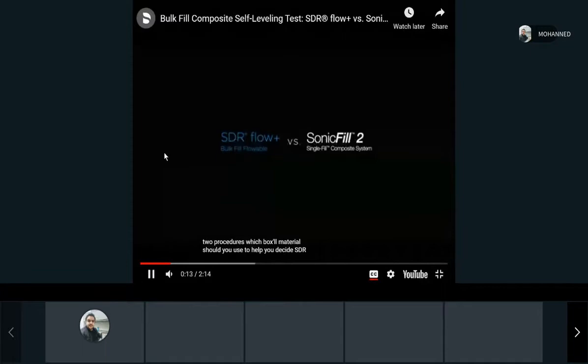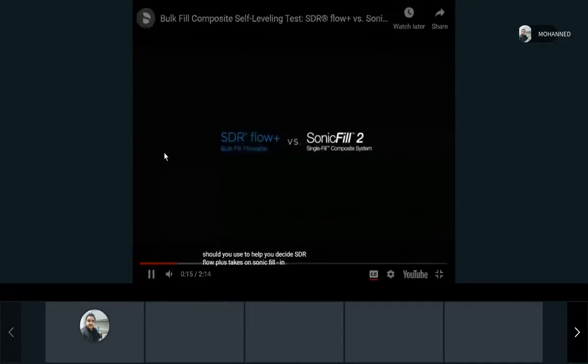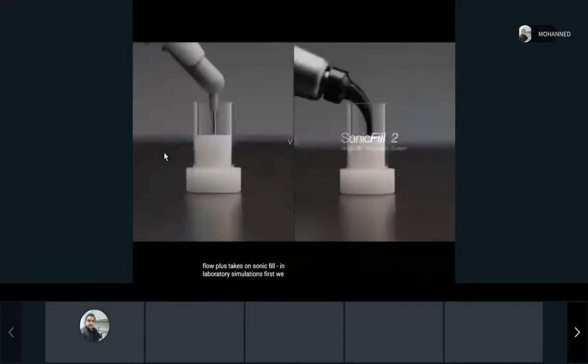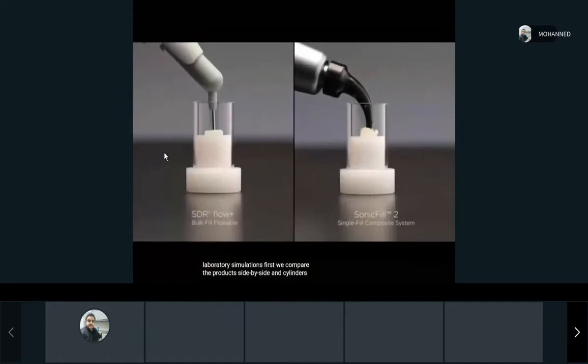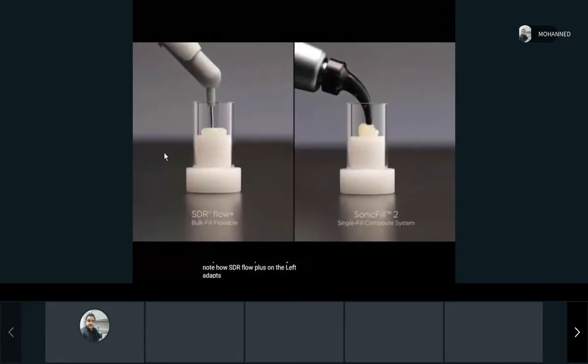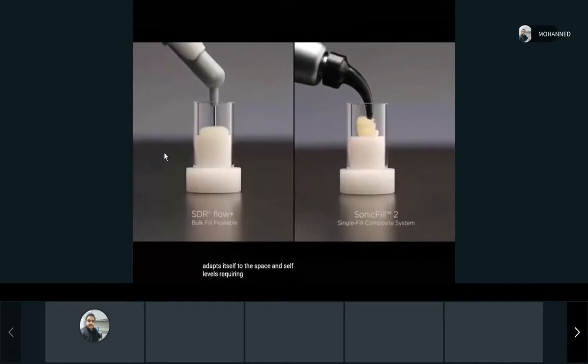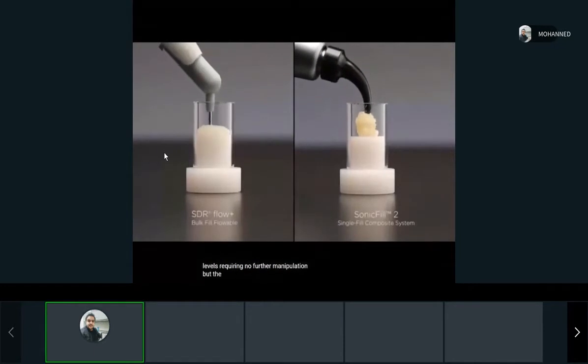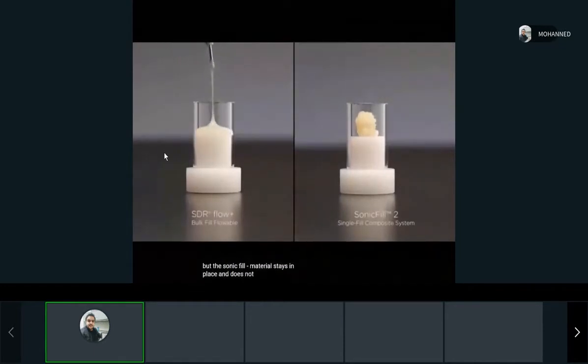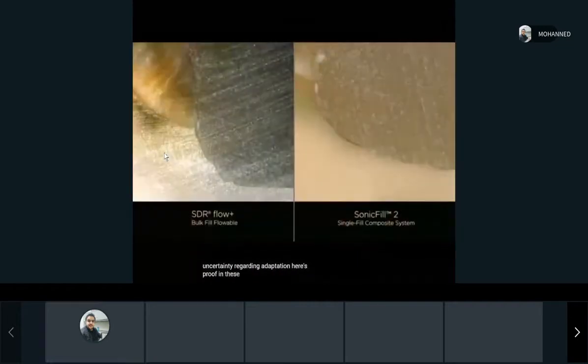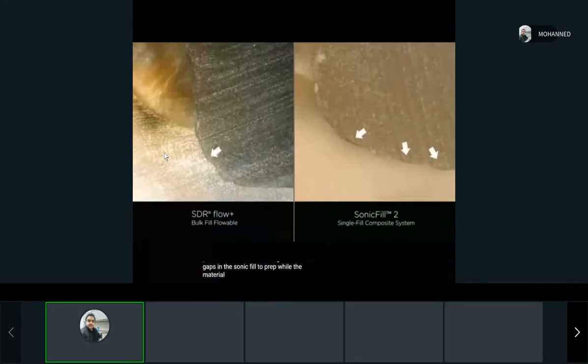To help you decide, SDR Flow Plus takes on Sonic Fill 2 in laboratory simulations. First, we compare the products side by side in cylinders. Note how SDR Flow Plus on the left adapts itself to the space and self-levels, requiring no further manipulation. But the Sonic Fill 2 material stays in place and does not self-level. It would require an instrument to manipulate and adapt it to the walls of a prep, which can be time-consuming and may provide uncertainty regarding adaptation. Here's proof. In these two SEM images, notice the gaps in the Sonic Fill 2 prep, while the SDR Flow Plus prep is gap-free with excellent cavity adaptation.